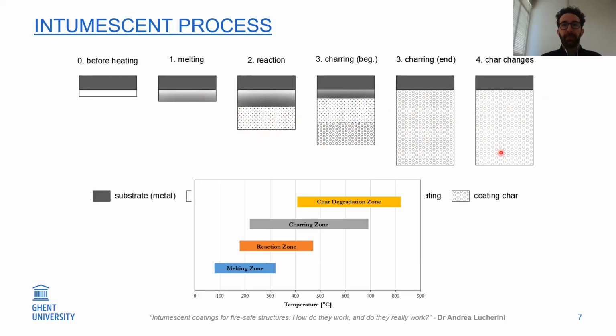This process usually occurs in four different zones. They are usually characterized by different temperature ranges based on the different fire exposure, but also the different products. The first one is the so-called melting zone. Then there is the reaction zone, the charring zone, and the char degradation zone. As you can see, there is a big scatter in the temperatures because in the literature you can find a big amount of different products and different fire exposure and heating conditions.